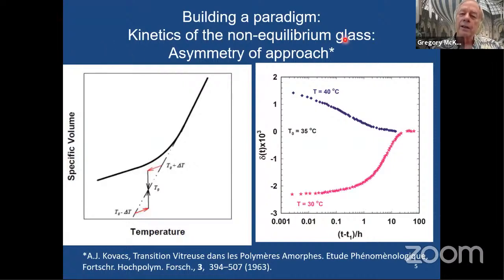Okay, another aspect of the Kovacs signatures is the asymmetry of approach. In this experiment, what we do is we start out in equilibrium at some test temperature plus delta T, and we'll do a down jump to the test temperature T0, or we'll go from T0 minus delta T, and we'll jump back up and do an up jump. So we have a down jump and an up jump. And if we had a linear process, the departure from equilibrium as a function of time should be a mirror image in the two. Okay, so here we see the down jump proceeds more rapidly to get into equilibrium than the up jump. So we have a strong asymmetry this way in the vertical axis.